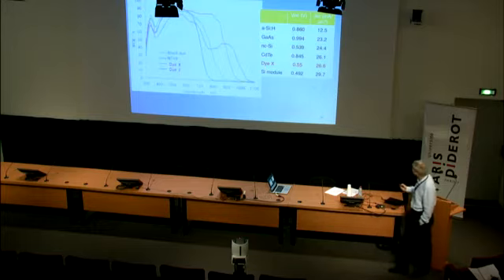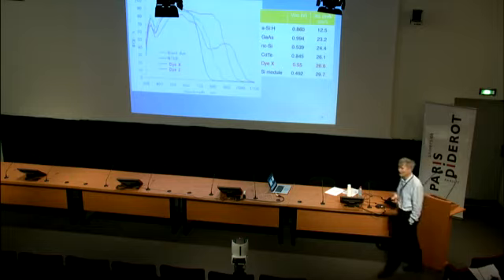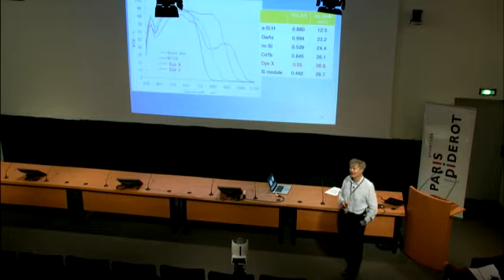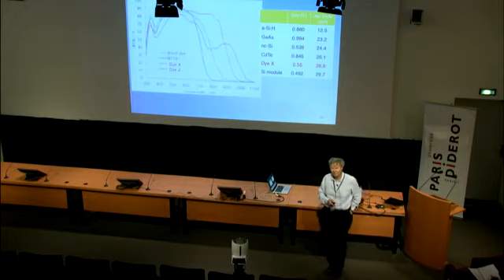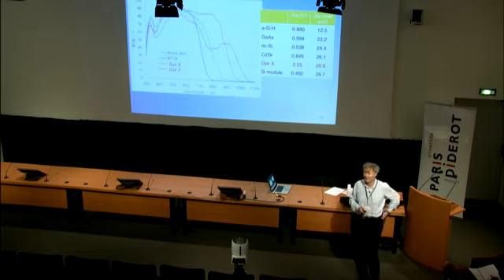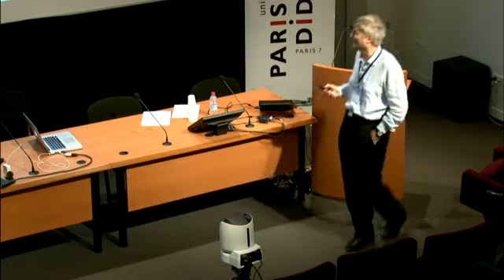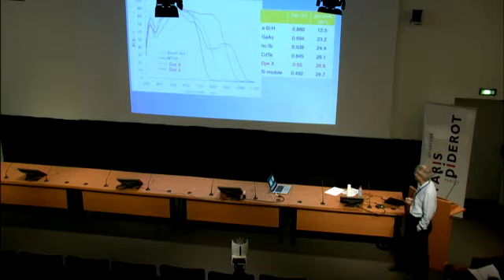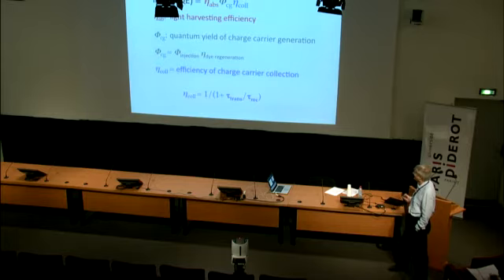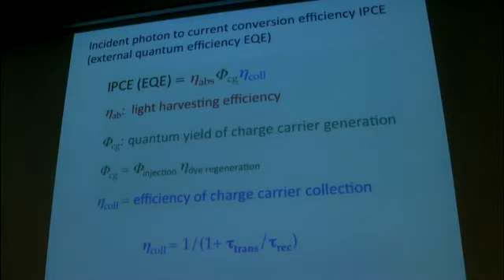Well, what is the structure? Well, Dye X. So be my guest, but I have to tell you the structure is now known. I know the structure, I can't tell you. It still is confidential. It's a ruthenium complex. And so it's amazing you can get that optical response. And so the high IPCE values show that even with these panchromatic systems, you get good carrier collection.